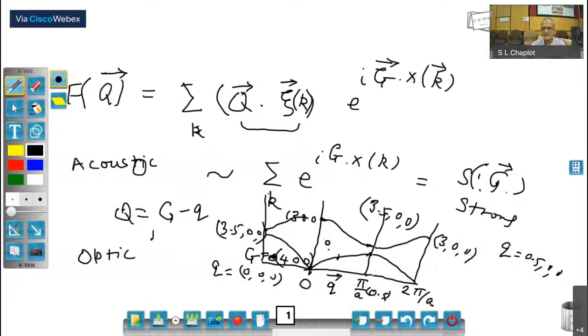The important things we've talked about so far in detailed phonon measurements: first, it is important to see the orientation of the resolution ellipsoid, and we try to choose the vectors in such a way that we are parallel to the resolution ellipsoid. Second is choosing the value of G.